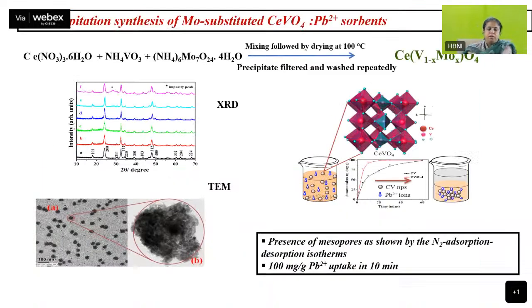Okay. This is one example from my own work. We wanted to synthesize cerium vanadomolybdate. We took cerium nitrate, we took ammonium vanadate, and then ammonium molybdate. So my anion was vanadomolybdate. So I took the ammonium salt of both. Okay. I mixed them, I heated them at 100 degrees. Water evaporated. And once I got the precipitate, I filtered that precipitate from the water that was formed.